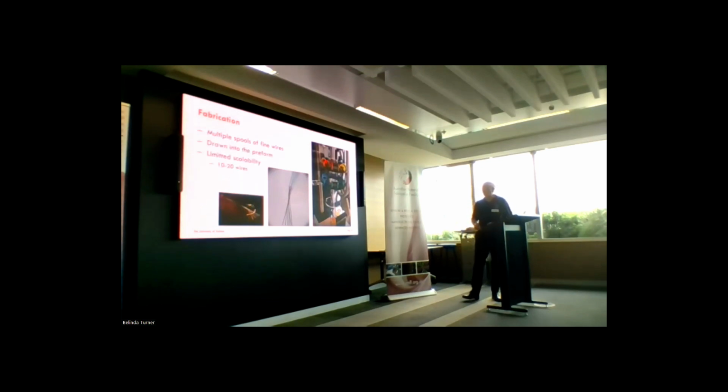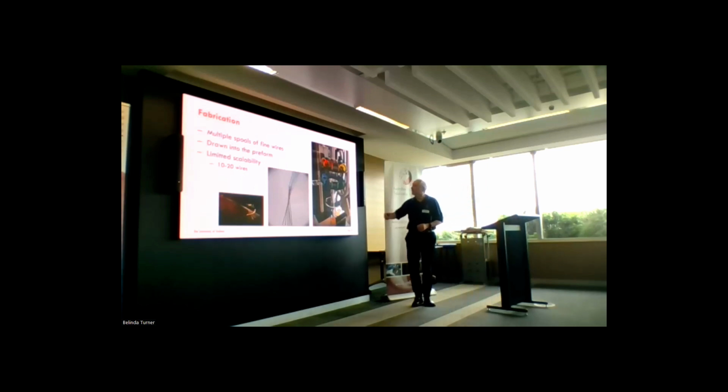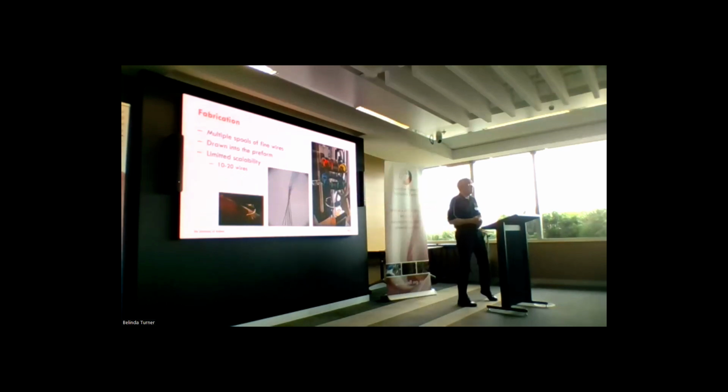reasonably well, but unlike the 500 wires we got with indium, it has limited scalability. This is quite a contraption, and the more wires you add, the more spools, the more chance something's going to snag and break. That's got 12 wires in it. I don't think you'd really want to scale that up much more than that, but it is a good way of drawing in high melting temperature metals, things like tungsten and platinum and so forth.